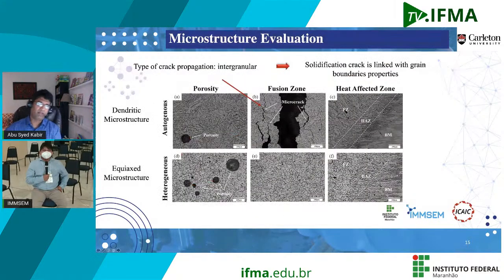And if we look at the microstructure in autogenous and heterogeneous joint, there is a big difference in microstructure. What we can see in autogenous, or let's say without the presence of titanium carbide nanoparticle, the microstructure in the fusion zone is kind of like dendritic, whereas the microstructure in the fusion zone for a heterogeneous joint is no longer dendrites but is equiaxed. Titanium carbide nanoparticle changes the morphology of the microstructure from dendritic to equiaxed.